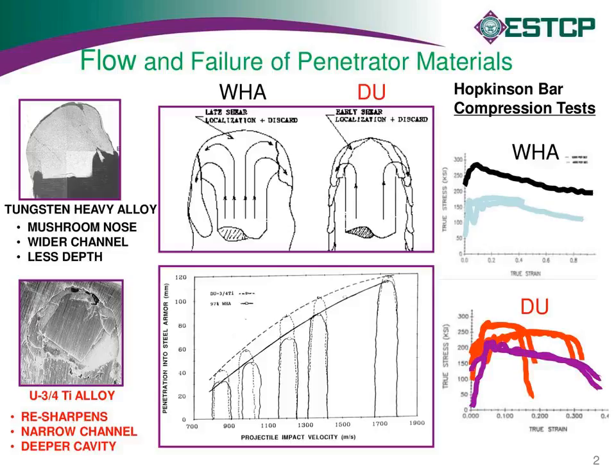It builds up a bit of a head, then discards it, and then builds up a bit of a head and discards it. So as a result, you end up with a very roughened penetration tunnel, but on the average much narrower than the tungsten heavy alloy tunnels. So at the very highest velocity, 1700, they're pretty close. Is that what I'm reading from this? Yeah, that's right. In terms of effective range on the target, though, the difference is still there.